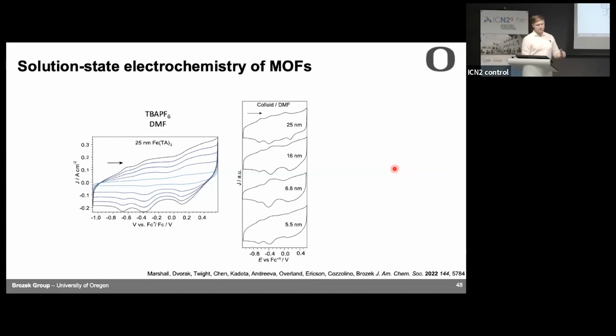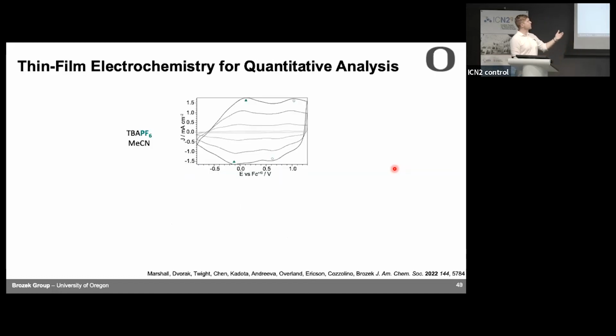So we wanted to get a little bit deeper insight into what's causing this. And so we cast them as thin films, because now we can do that. Cast them as thin films on a glassy carbon electrode. We used acetonitrile since they don't suspend in acetonitrile. We see CV traces that are pretty similar. So multiple pretty reversible waves. This is all done in TBA PF6.